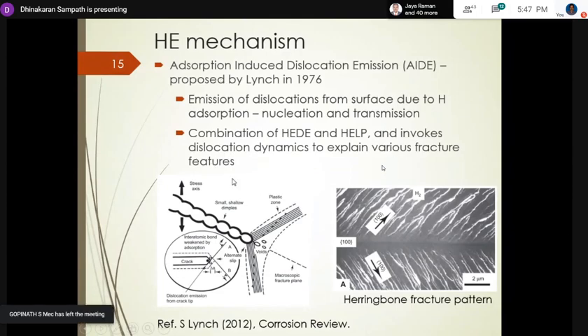There are several models, but for this presentation, I took the most important three. Adsorption-induced dislocation emission: once the hydrogen enters the surface, it creates a dislocation and helps to move the dislocation, which means we get this localized shearing, and at the intersection it forms voids that lead to continuous cracking. As the name says, this is adsorption-induced dislocation emission, and it explains the herringbone fracture pattern very much,